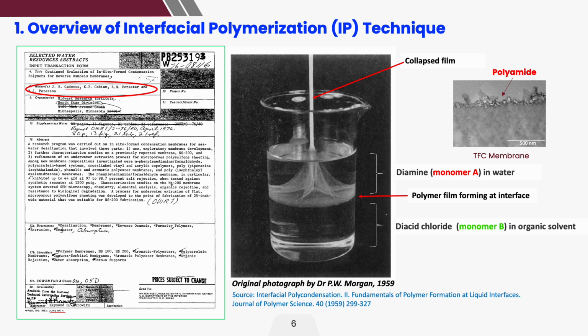This technique was actually invented by Dr. P.W. Morgan in 1959. So at the time, P.W. Morgan demonstrated that if you had two different immiscible monomers, and once they meet each other, they can start to cross-link with each other at room temperature.